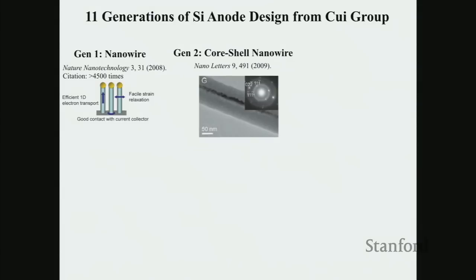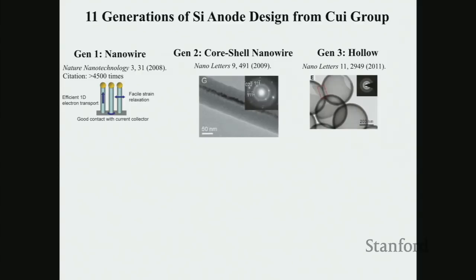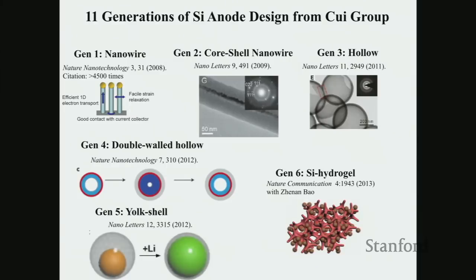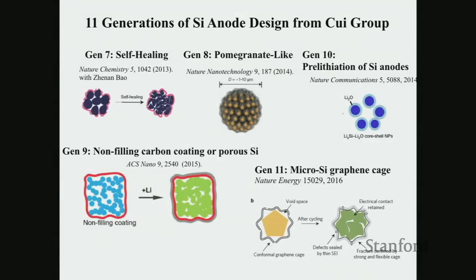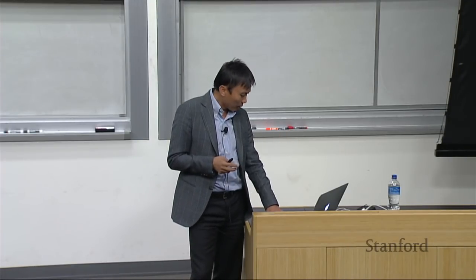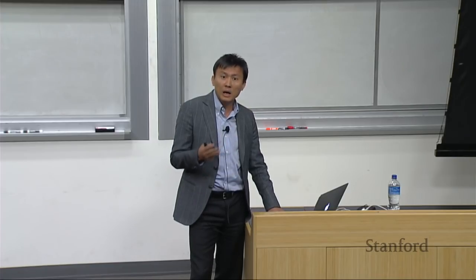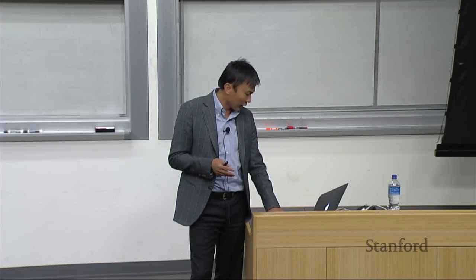We go to the core shell design, using a stable core to stabilize the whole structure, which is getting better. Then hollow structure design, so you can have interior hollow space and more volume to relax the strain. We have been through 11 generations now. Each generation, we try to solve one problem. And you can see all this learning stacking up. Now we start to build up the material design principles for industry to use, and eventually to solve the problems of volume expansion, breaking, and instability of the solid electrolyte interface.